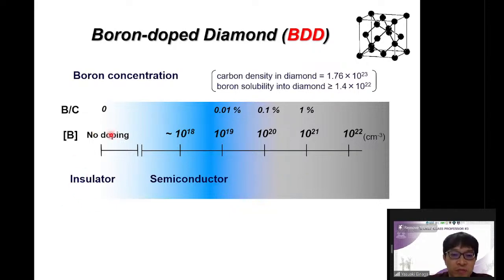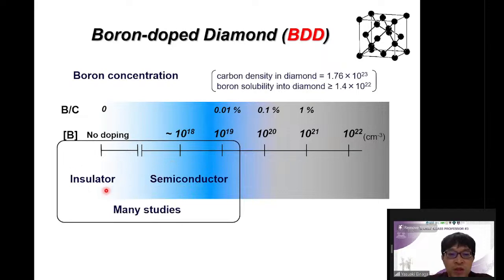Okay, so diamond is an insulator, as you know, but the important point is to dope boron. When the boron is doped in very low concentration, the conductivity increases. This is the boron concentration like this. When the boron concentration is low, this shows a p-type semiconductor. This insulating diamond and semiconducting diamond are studied by many people, so these studies are very popular.